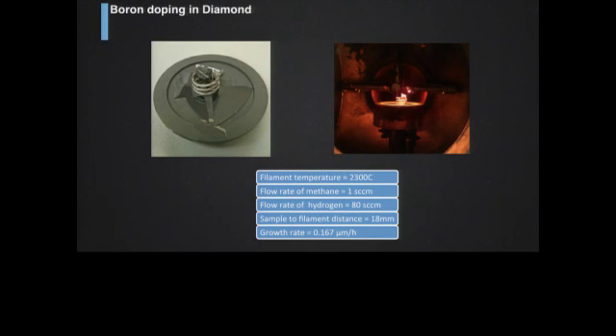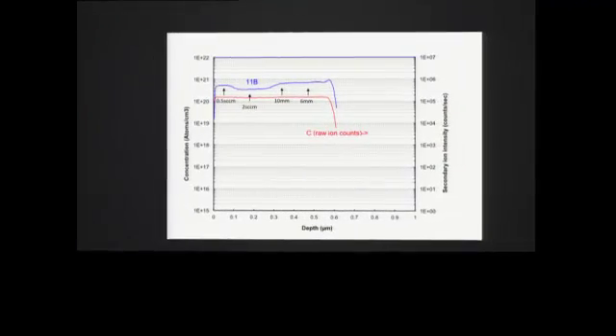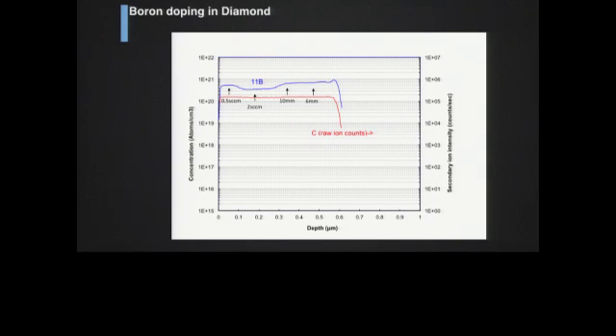So how do we put traditional boron in? We've used a boron oxide, and this is an actual picture of our little container of the boron oxide as we actually grow the sample. And these are the growth parameters. This is some SIMS data from typical growth under certain kinds of pressure conditions of the gas flows.